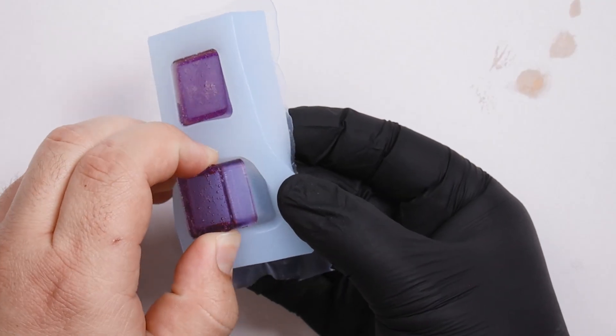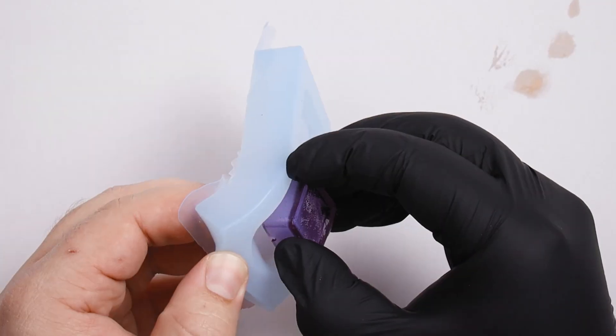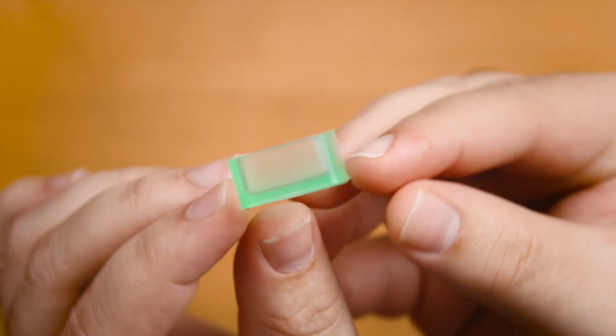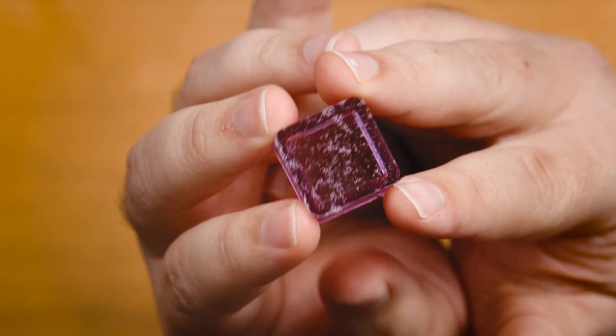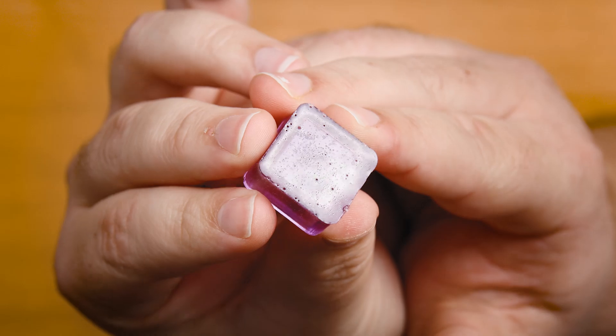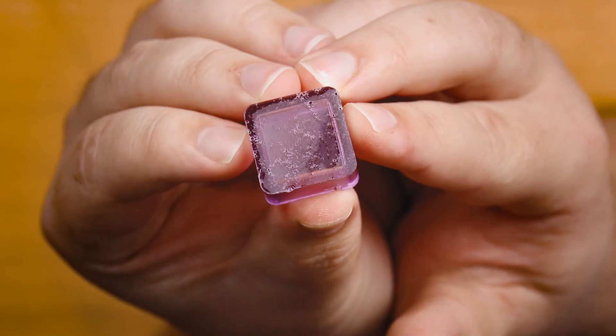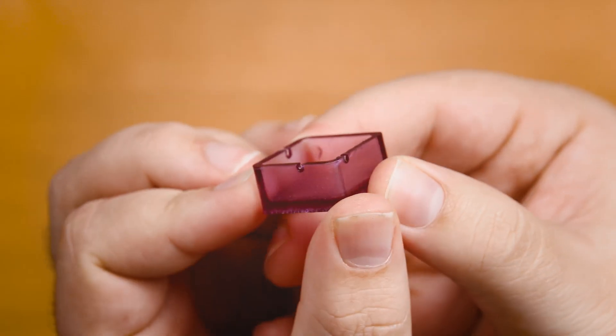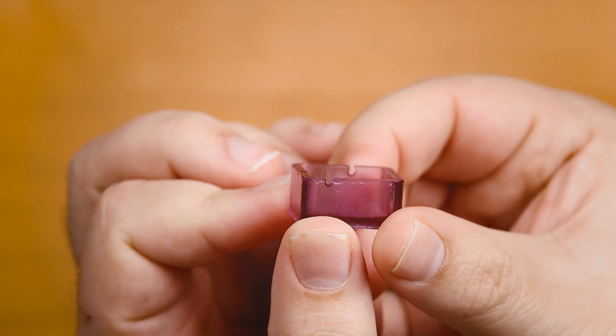It's pretty straightforward to make batches. And I did get some bubbles in my first batch, but my second one, I left the resin a little bit longer before pouring, which really helped. And for us, it didn't really matter, but these top bubbles can be fixed with a quick heat of a blowtorch, or if you're really pedantic, you could use a vacuum chamber, which completely eliminates all the bubbles.